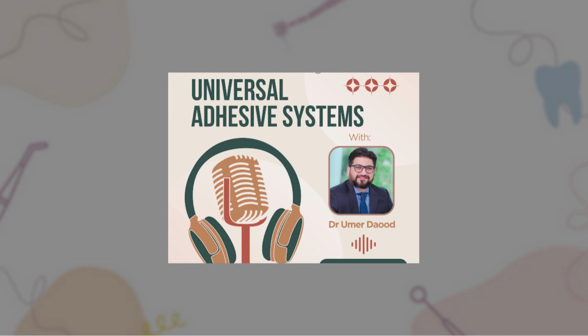What is ethanol wet bonding? Alright, so let's begin by understanding what is there within the adhesive system, right? There is a water-rich zone, which is very rich in polymerized or unpolymerized hydrophilic monomers along the resin-dentin interface that comes from the adhesive, and it's present inside the hybrid layer, and that continues to be a problem. So even if the collagen matrix can be preserved, the loss of integrity through the degradation of the adhesive component will always remain.